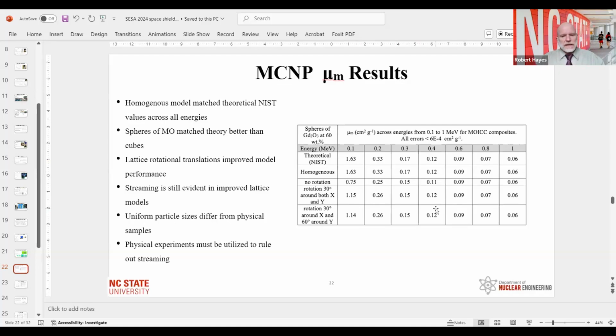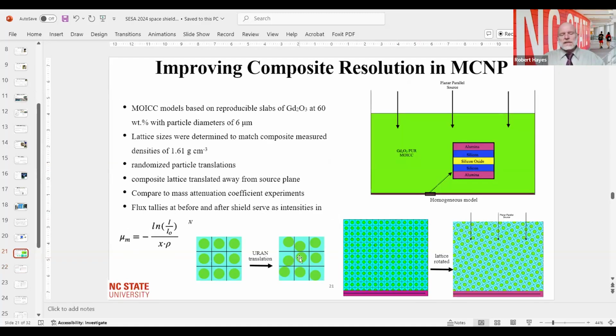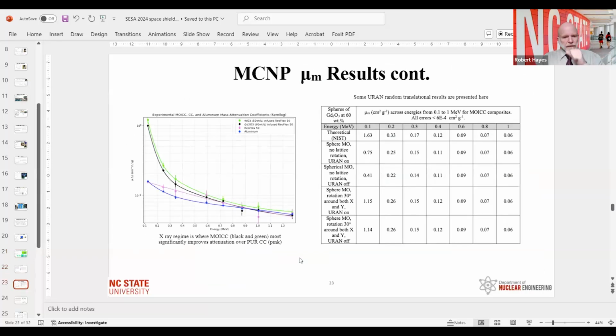And so what that's telling us is that these high Z metal oxides, they're very powerful at attenuating low energy photon or beta, but they're not so great at attenuating gamma. They don't make a big difference at really high energy photons. They only make a big difference at low energy photons, which is where you now see a difference. And so that was a big discovery for us.